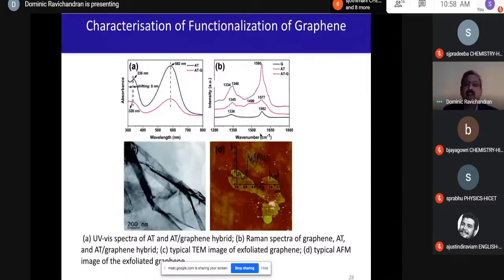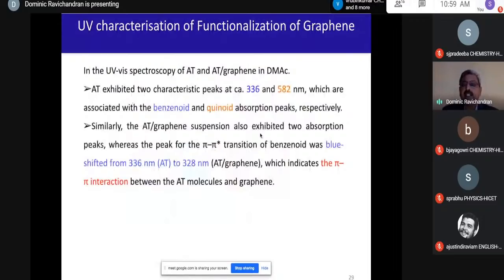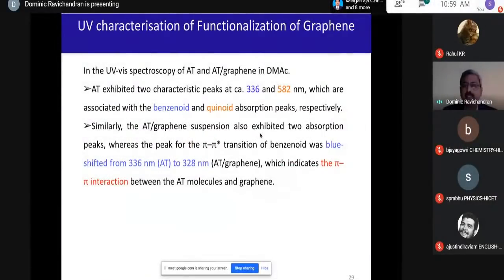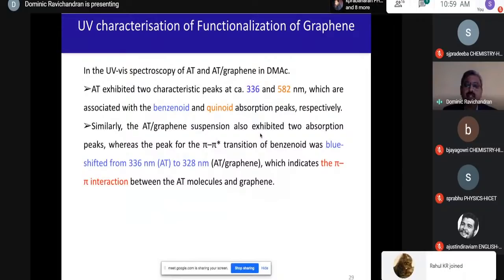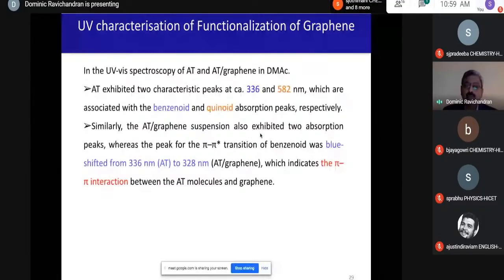In the UV visible spectroscopy of aniline trimer and aniline trimer graphene in dimethyl acetate, the aniline trimer exhibited two characteristic peaks at 336 and 582 nanometer, which are associated with the benzenoid and quinoid absorption peaks, 336 for the benzenoid and 582 for the quinoid absorption peak. Similarly, when you record the spectrum for the aniline trimer graphene suspension, it also exhibited two absorption peaks, whereas the peak for the pi-pi transition of the benzenoid was blue shifted from 336 to 328, which I've indicated in the graph. And this confirms the pi-pi interaction between the aniline trimer molecule and the graphene.